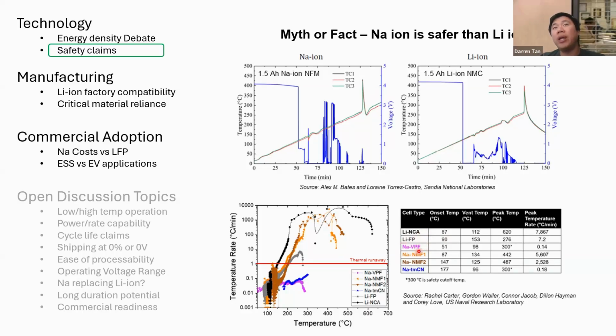Subsequently, they also obtained a sodium polyanion chemistry. This is the vanadium phosphate doped with fluorine, obtained from Tiamat batteries in France. When they did the same test on it, it hardly had any heat generated at all, and the temperature rise rate was extremely low. It's not even 1 degree a minute. So it was concluded that this polyanion did not undergo thermal runaway, which is really exciting.